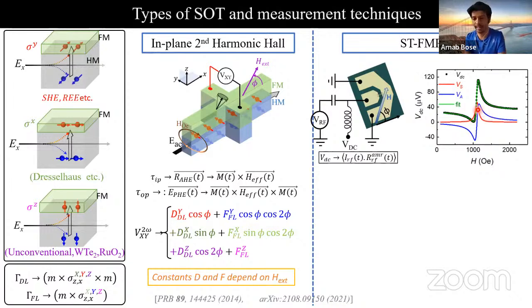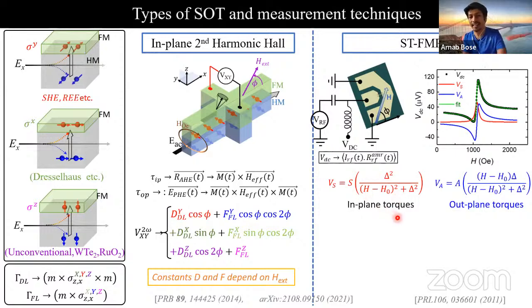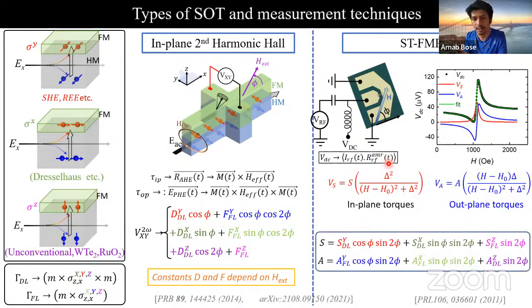And because of the resonance, we can get the symmetric and anti-symmetric Lorentzian. With this, we fit the data. From the symmetric Lorentzian, we get the in-plane torques, and from the anti-symmetric Lorentzian, we get all the out-of-plane torques. Now we repeat the experiment by applying the magnetic field at different angles phi with respect to the current flow direction to get the angular dependence of the symmetric and anti-symmetric Lorentzian. Again, there are 6 terms and 6 unknown types of torques. By fitting the angular dependent symmetric and anti-symmetric Lorentzian, again, we can identify and quantify 6 different types of torques. So these 2 techniques we have used in our experiment.